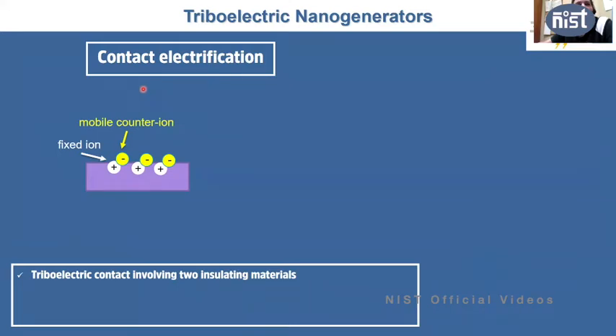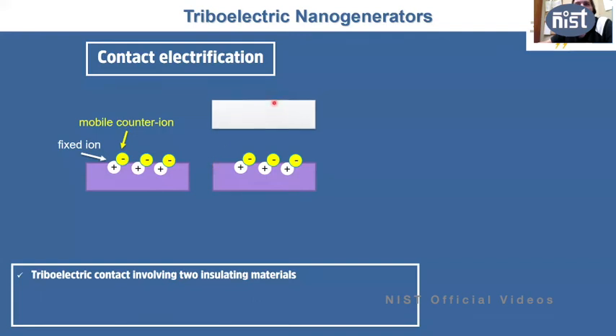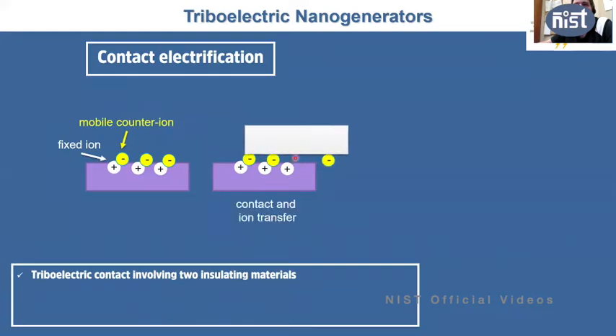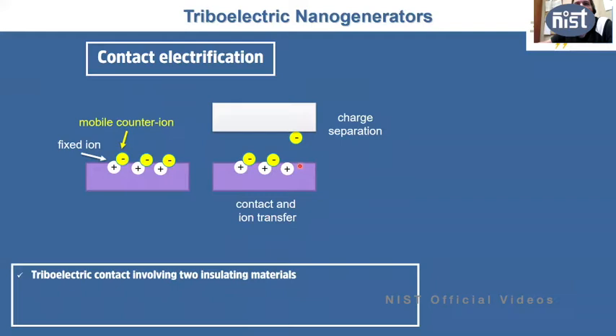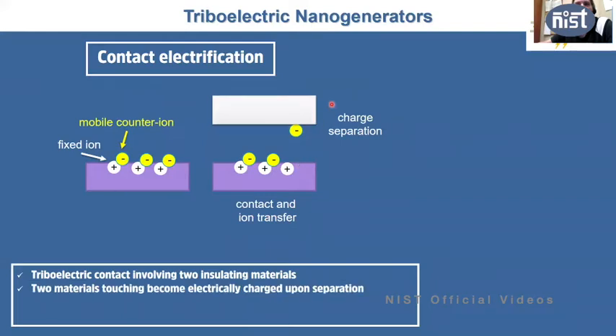You typically on these triboelectric generators have two insulating materials. If you consider one of these, they typically have one fixed ion and mobile counter ions. If you put one of the materials in contact with the other, either in contact in the horizontal direction or in sliding, one ion can be captured by the other material. And when you separate the materials, you have charge separation, and the materials become electrically charged.